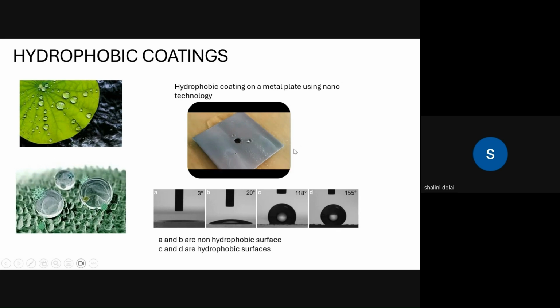How did we achieve it? We took one siloxane coating. Siloxane coatings are known for their low surface tension, and then we added nanoparticles of SiO2, iron oxide. We explored different types of iron oxide shapes, spherical, cylindrical, then zinc oxide also we explored. Among all, SiO2 was giving the highest hydrophobicity, and that's how we achieved this coating. This coating is being used on car windshields in high-end cars, where whenever there is fog in the atmosphere or rain, the glass will be clear.